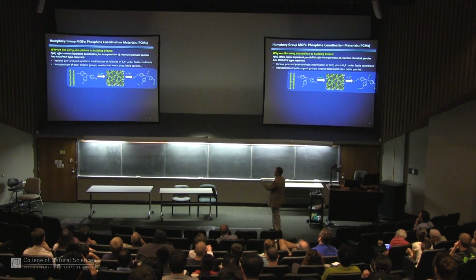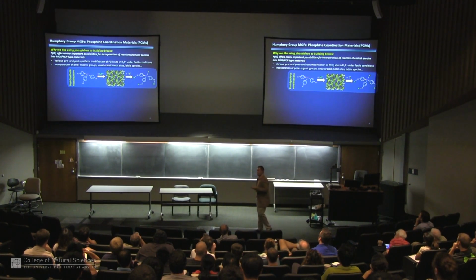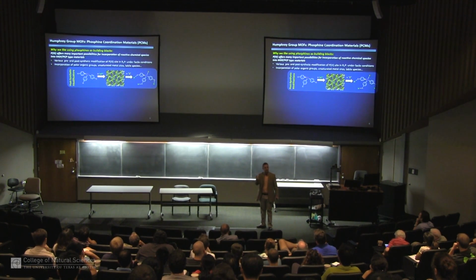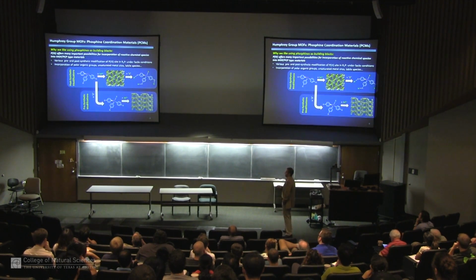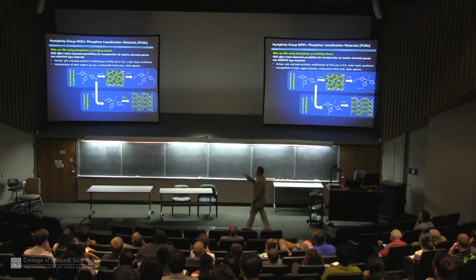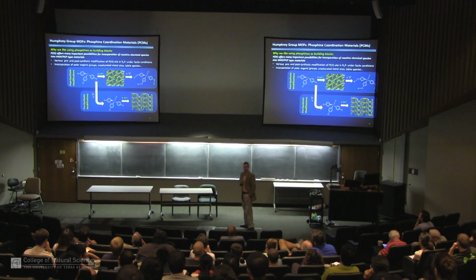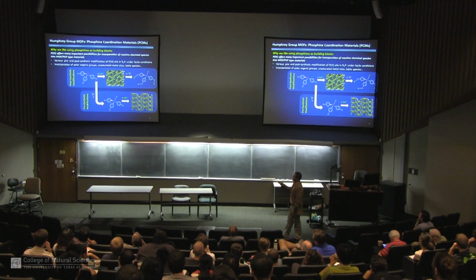And it has these abundant phosphine sites that we can then do post-synthetic chemistry and attach things and tether things into the pores. Why is this good? Instead of making a whole library of MOFs for different purposes, we can just make one MOF, and we can post-synthetically change it to whatever application we're interested in by using this phosphine as a handle. And there's an extra plus, we can do pre-synthetic organic chemistry, so we can plug things onto the phosphine sites beforehand, and then we find if we use exactly the same metals and the same conditions, we make completely different materials because we've already done the chemistry in a different order. So we get lots of different opportunities for these things. The stumbling block is making these, but they're the means to an end to get to our materials.